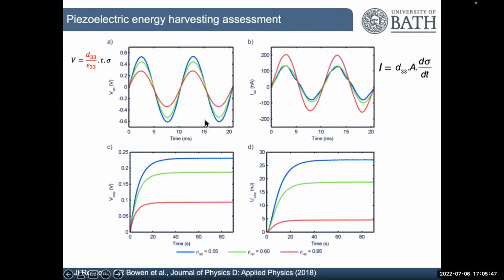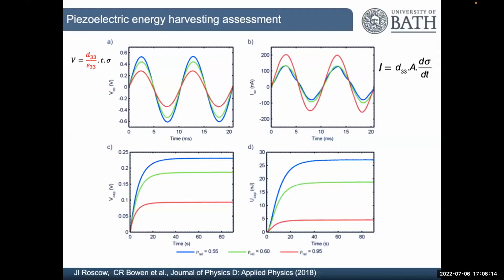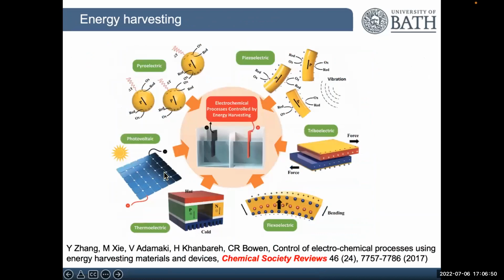So this is the voltage against time as it's oscillating on the shaker. The blue is the porous material, 55% porous. The red is the more dense material, the standard material. And you can see that the blue porous material generates a higher voltage, and that's because of the lower permittivity. And so it's a better sensor, or if we had particles within an electrochemical system, we'd be developing a higher voltage. The current is reduced, but if we look back to our basic equations, that's not surprising, because the current is related just to d33. It's got nothing to do with the permittivity, and we won't be able to pole as well, making it porous. So we do expect it to fall, but power is a combination of voltage and current. And so when we look at the energy or the voltage stored on the storage capacitor, the porous ceramic wins outright. And I'll move on now to electrochemical systems.